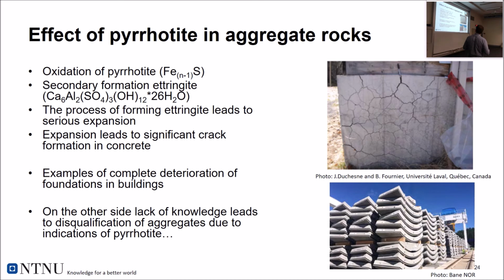Formation of a secondary mineral, which has a complex formula and that varies. It's a result of oxidation of pyrrhotite. When pyrrhotite reacts with other material in the cement and forms this mineral, it expands. Expansion is again a problem. And this is the foundation of a house that has total deterioration because of that. All the pyrrhotite spots in the aggregate resulted in this happening. So most of the 1,000 houses in this area have to be rebuilt. They have to change the entire foundation.